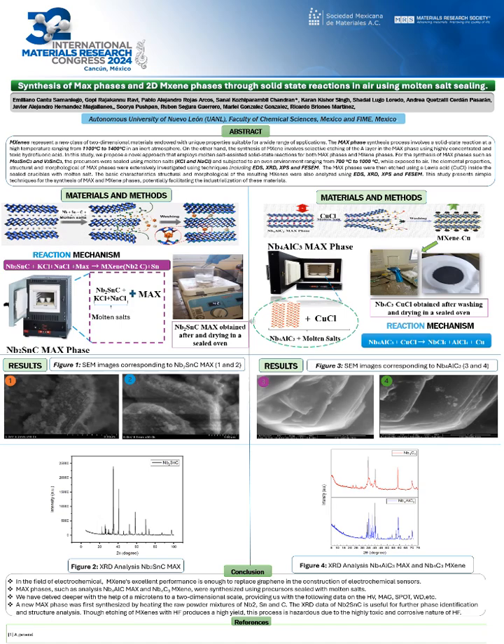For the synthesis of MAX phases, such as Nb2SnC, the precursors were sealed with molten salts using KCl and NaCl respectively, and subjected to an oven environment ranging from 700 to 1000 Celsius degrees while exposed to air. On the left side of the poster, you can identify the reaction that is taking place while being in the oven, using the MAX, in this case conformed of Nb2Sn and C, with the molten salts being KCl and NaCl. This process is being done at 750 Celsius degrees for around 12 hours.